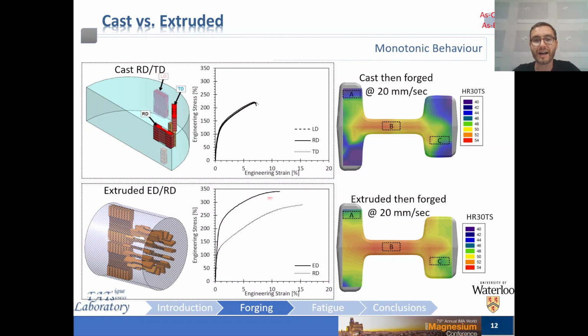You can observe that the cast material has identical properties in all three directions. And this differs from the extruded material, which is anisotropic in its response, which is a well-documented phenomenon that many of you may be familiar with. Furthermore, there's an obvious difference between the two, with the extruded material having a much higher strength and enhanced ductility, which is typical of wrought forms of magnesium alloys.